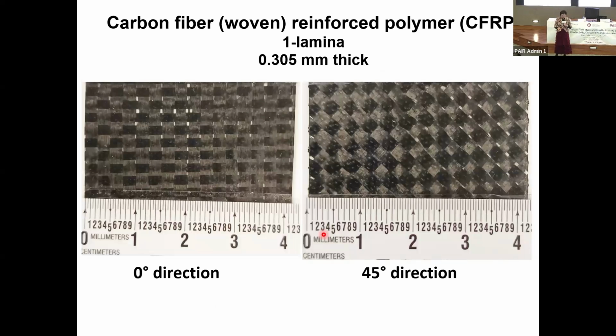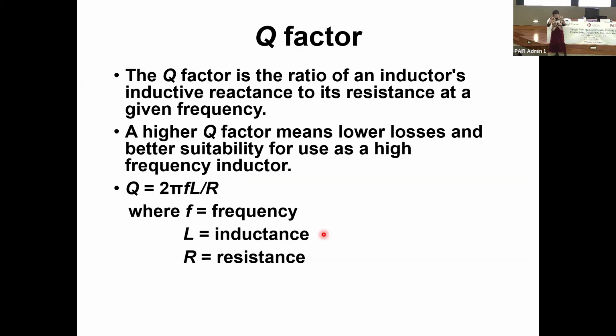So we measured the inductance of continuous carbon fiber woven reinforced polymer, CFRP, just one lamina, but woven like this, looking at the 0-degree direction horizontally and 45-degree direction horizontally. Just in case you haven't heard of that, the Q factor is important for inductors. It is the ratio of an inductor's inductive reactance to its resistance. And the higher Q factor means lower loss and better suitability for use as a high-frequency inductor. And it's just given by this simple formula.